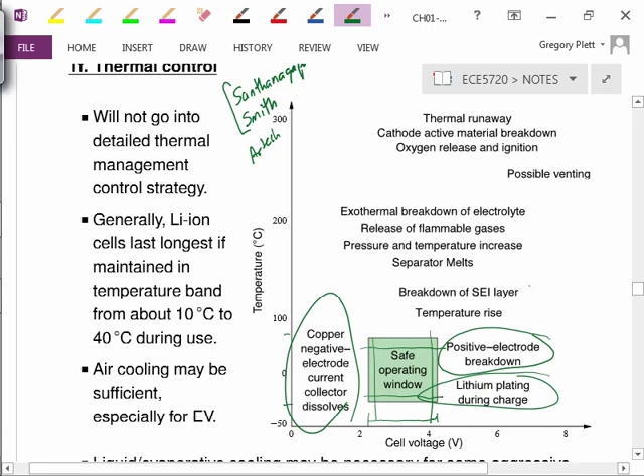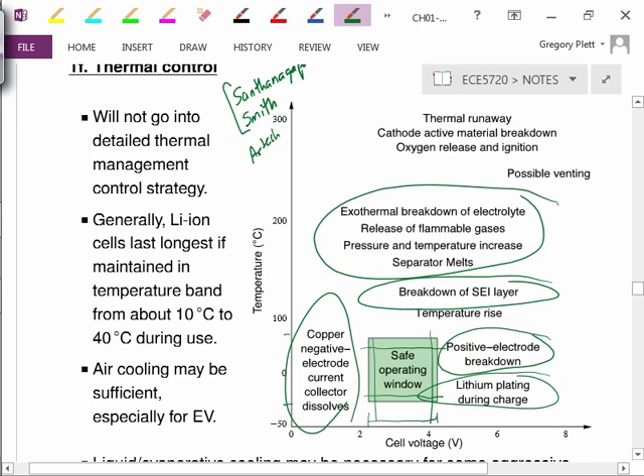And at much higher temperatures, the solid electrolyte interphase layer on the negative electrode breaks down, and then new SEI forms. You have very rapid capacity loss. We also have, at higher temperatures, the electrolyte breaking down in an exothermal reaction, which means that it's releasing heat while it's breaking down, which generates more temperature, and you end up with releases of flammable gases, and pressure increases, and the separator melts, and then you have short circuits. The gases might build up enough pressure that you vent these gases into the atmosphere, and some of them are combustible, like hydrogen gas is one possible outcome, which is combustible.